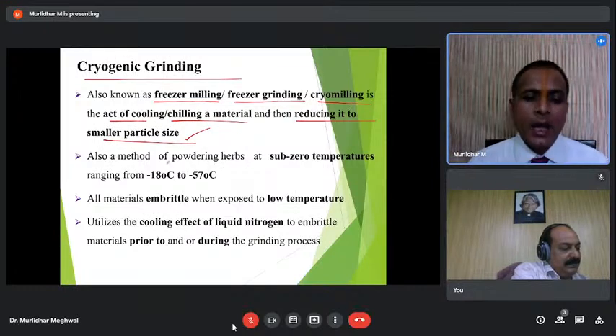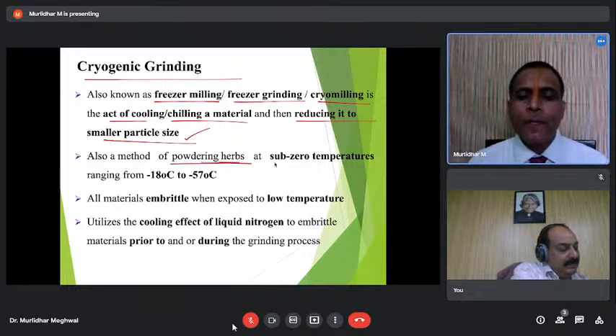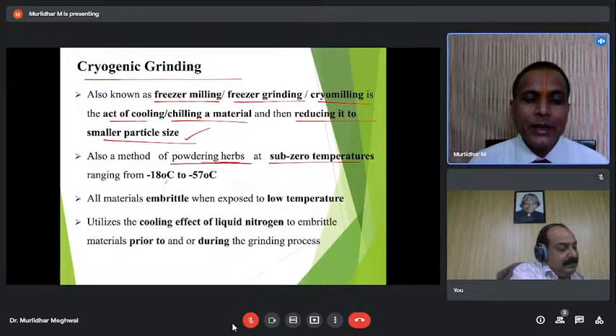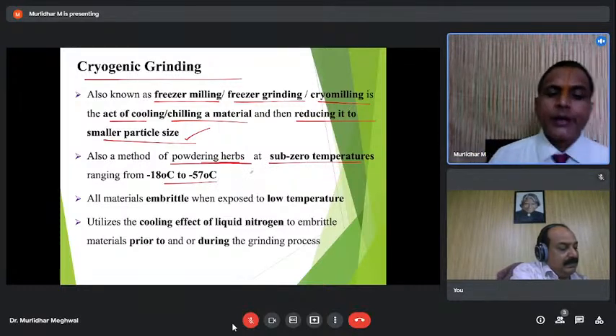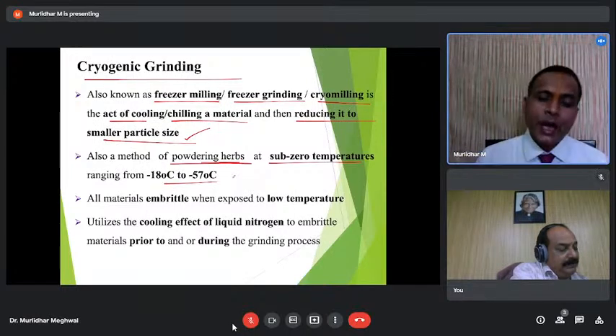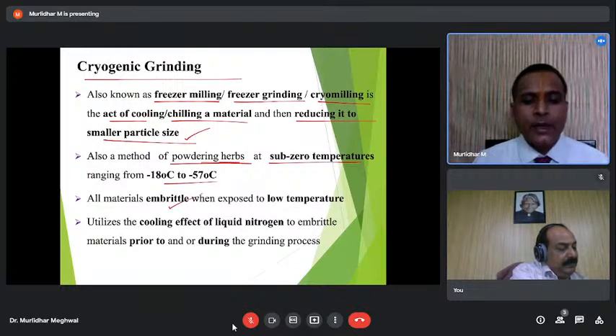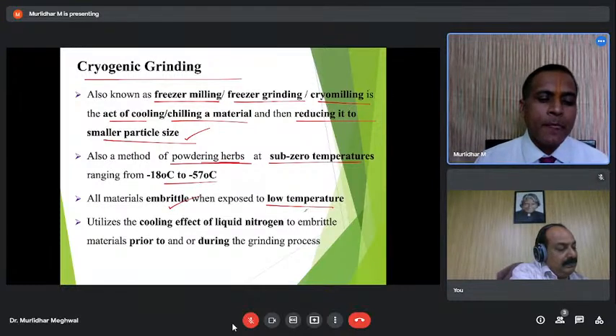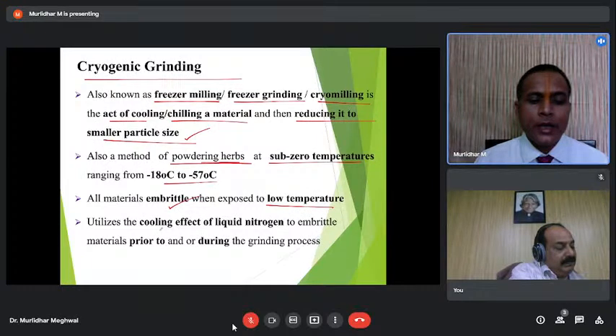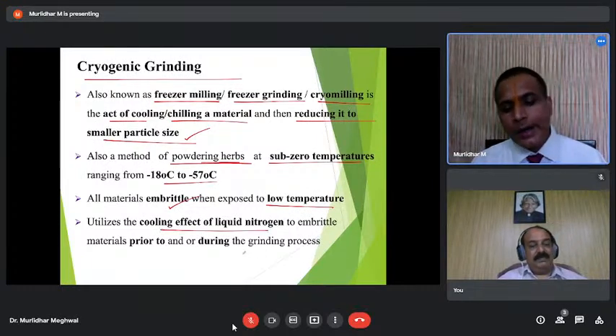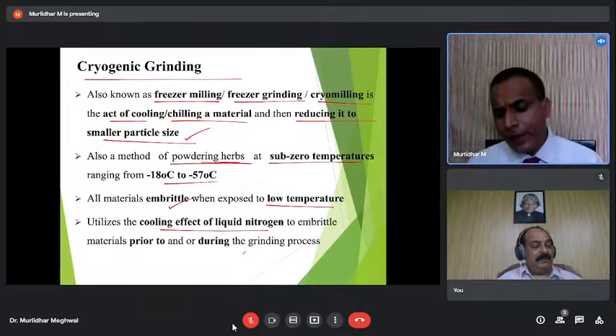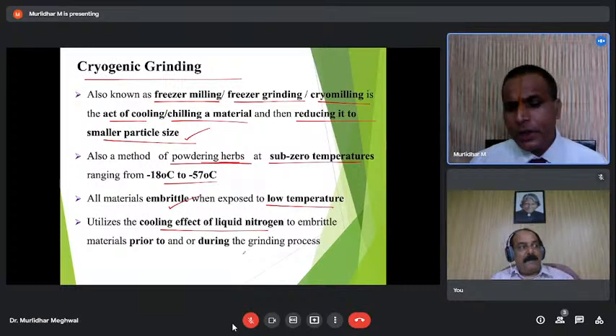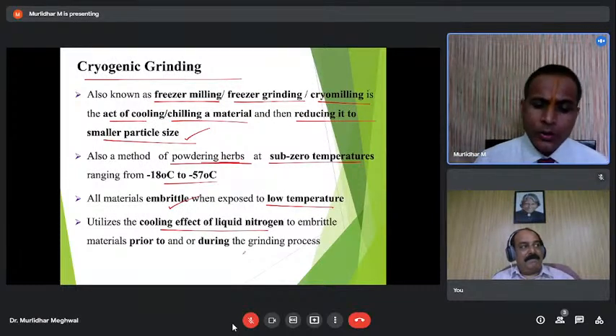And as we discussed, in Ayurveda and in medical fields also, it can be used to make powder of herbs. With very low, sub-zero temperatures, ranging from minus 18 to minus 57 degrees, they can retain all the phytochemicals in the spice or herbs which are good for health. All the materials become brittle when they are exposed to low temperatures, so it becomes easy for grinding. It utilizes the cooling effect of liquid nitrogen to embrittle materials prior to and during the grinding. So we can do pre-cooling, pre-chilling, and then grinding, or during the grinding also we can supply the liquid nitrogen.